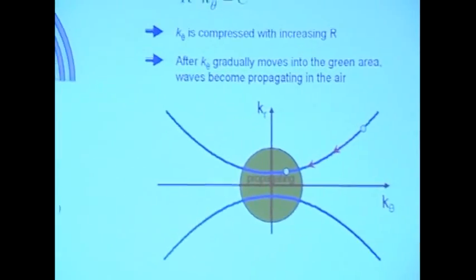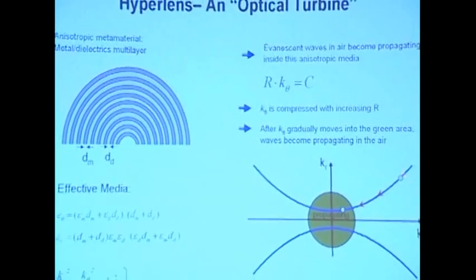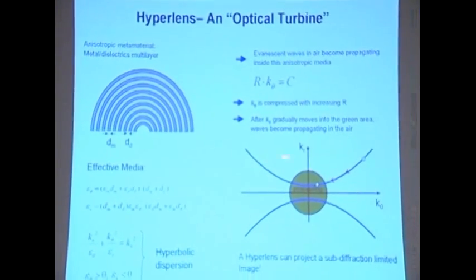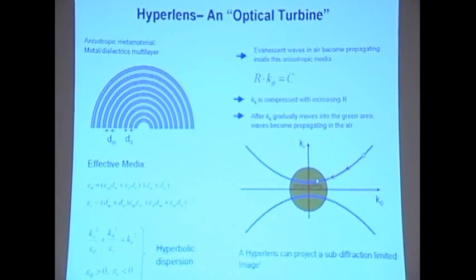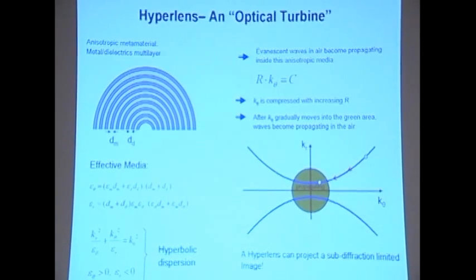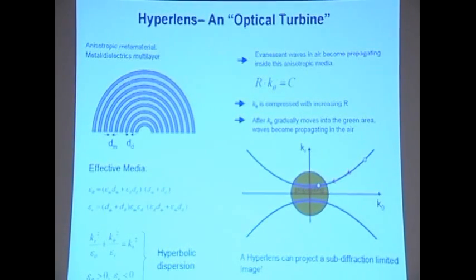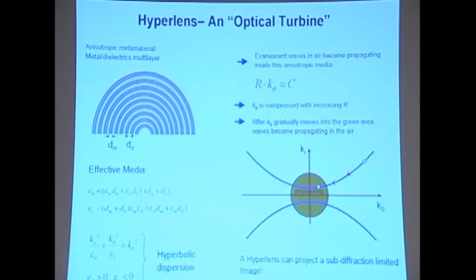When you fold your arms in on the ice, you spin faster, and when you extend the arms out, you spin slower, right? So when this wave propagates out, the tangential component has to be conserved, such that as R goes larger, K theta has to get smaller. So you continually compress this tangential K component until you reach the propagating band in the vacuum. And that is essentially like a photonic compressor. You compress the momentum all the way, continuously.